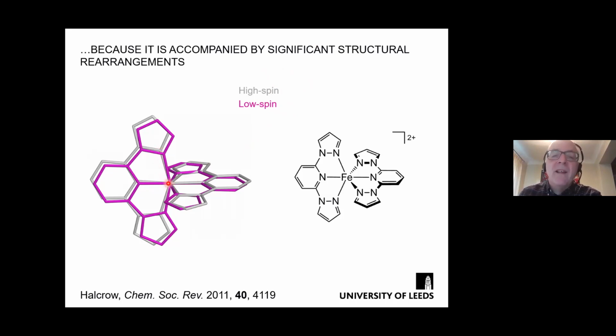The iron nitrogen bond lengths here change by about 10%. And of course, this changes in the inner core of the molecule. It's in the inside. But the outer surface of the molecule also must change to allow this inner structure change to take place. And it's that outer change that can lead to cooperativity in the crystal, because it's the outside of the molecules that are touching each other in the crystal lattice, not usually the inside part of the molecule here. So it's what's happening on the outside around here that is actually important for this.